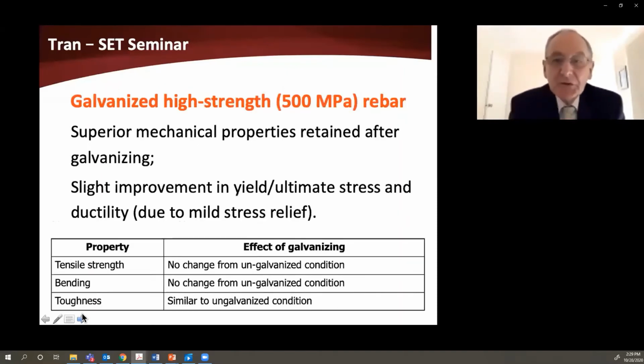Just to show you this sort of data, new high-strength galvanized bar getting up to 500 MPa. A question often asked is, what's the effect of galvanizing on the properties of the bar? Well, in fact, there is no specific effect. The temperatures of the zinc bath are only around the 450 degrees centigrade mark. This is well below any temperature to cause any significant change in the properties of steel. And it certainly doesn't change the properties of high-strength bars.